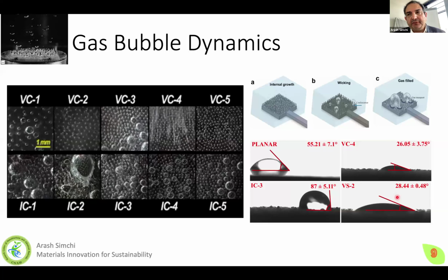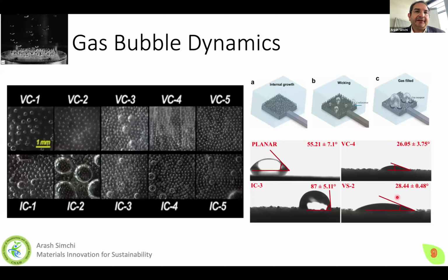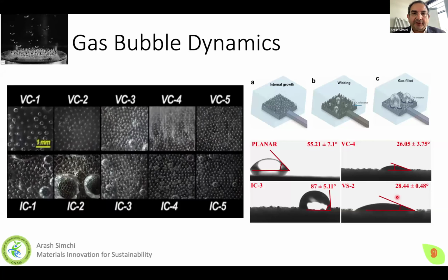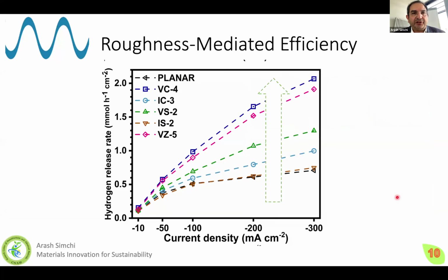This was a very nice example showing that we can learn from nature, design an electrode which is more effective. To show my concept, I would like to show you one example of hydrogen release rate versus current density for different electrodes with different configuration. See, this is a planar electrode, the lowest, and here is a vertical with a special geometry, and you see the hydrogen generation rate is much different. So the first lesson from nature is using a roughness-mediated approach, we can change and improve the efficiency of electrolyzers to produce green energy without even using very expensive materials.